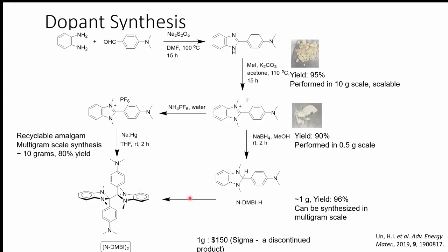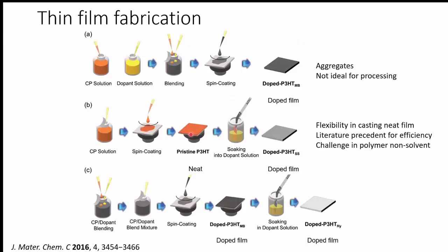Now, one thing that we wanted to try, which didn't work, is if we could somehow make this H compound by making a cation and then an anion and coupling them together to get a dimer, but that was not successful. But we have multi-gram scale of all of these, so this became a very easy thing after we optimized it. So now you might think, well, how are you going to process your polymer that is probably a brick dust plus this dopant into something you can measure, right?